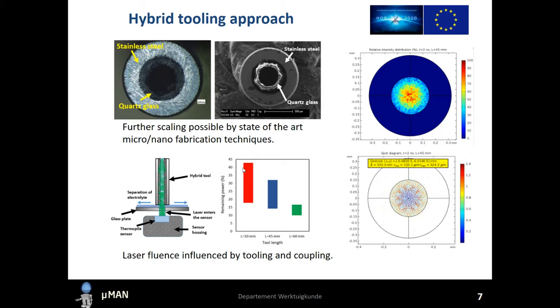Over a time period, it can drop to less than 20%, because there is solid deposition inside the tool electrode and we lose power. Of course, this power is also a function of tool length. As we increase the tool length, the power output decreases, because we lose some fraction of power in every reflection, and the longer the tool, the more reflections we have.